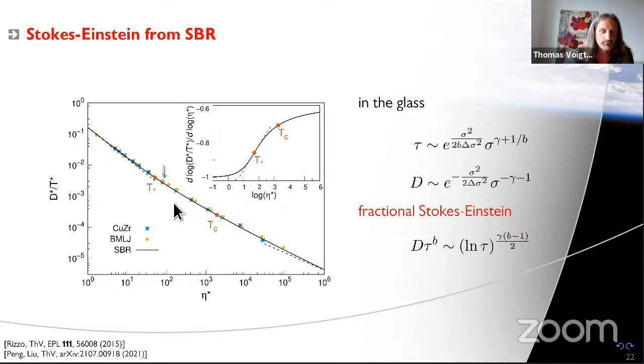And what I'm showing here are computer simulation data by Hailong Peng for the famous Kob-Andersen mixture, and also a model of copper zirconium. I mean, I work at the German Aerospace Center, and there are a lot of people interested in metals, and so we occasionally have to do something where the atoms have names. And so you see that for high temperature, high diffusivity, low viscosity, Stokes-Einstein holds, and then it crosses over to something that you can fit with a power law with an exponent that is not 1, not -1.